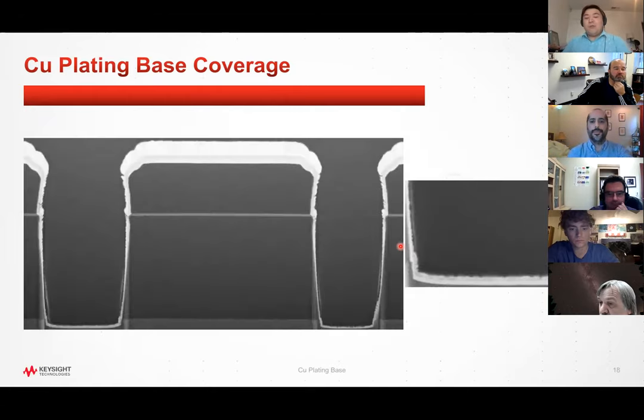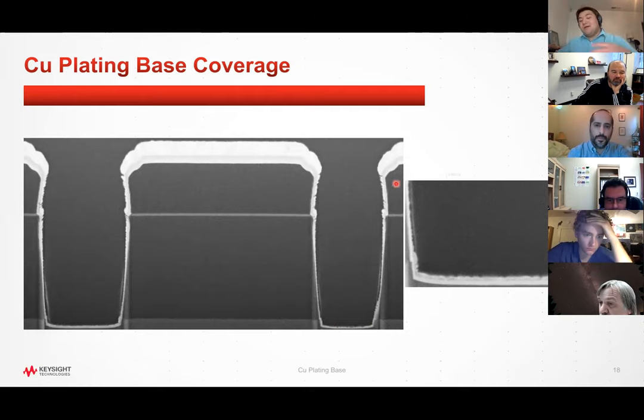And that was what some of my work focused on, was trying to get better coverage on the sidewalls, but also you notice what gets deposited at the bottom of the structure is a lot less than what gets deposited at the top. And what was happening in earlier samples was that in order to get what you needed at the bottom, there was so much at the top that when you go to plate it, it just seals off the top and leaves a giant void. A lot of it was around trying to optimize for better coverage at the bottom of these via structures.